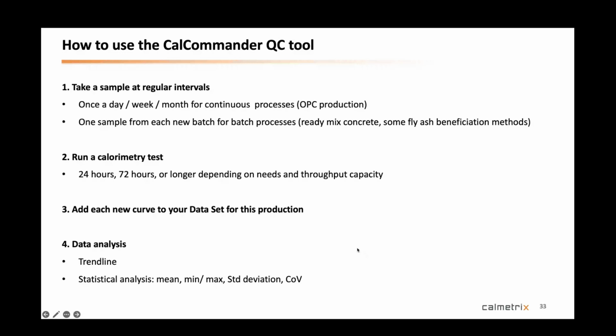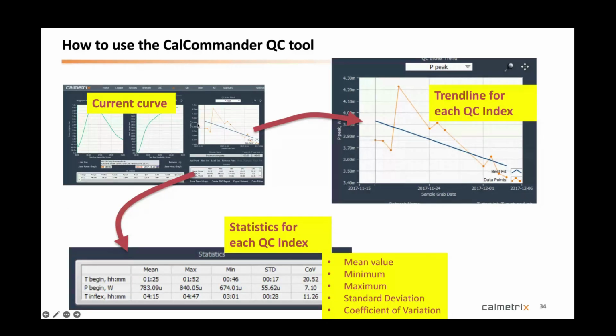You have a current curve. Now summarizing the current curve, you can add to your data set existing parameters for the curves from other days, from the days before, from other instances. Could be a few on the same day. And then you're able to visualize trend lines for each of the QC parameters here, that you can pick, and you're able to visualize statistics like the mean value, minimum, maximum, standard deviation, coefficient of variation, and it gives you a pretty easy way to assess how consistent your product is and trace it back to certain events. Of course, the software does not do this automatically, but if you somewhere have a logbook of things that you did on certain days, you'll be able to understand why those changes occurred, like they did in this particular example from that Canada plant.